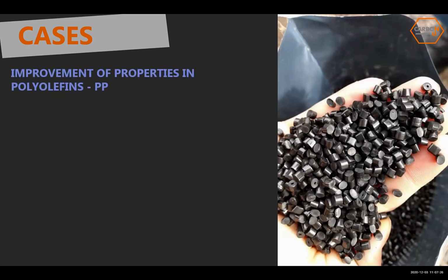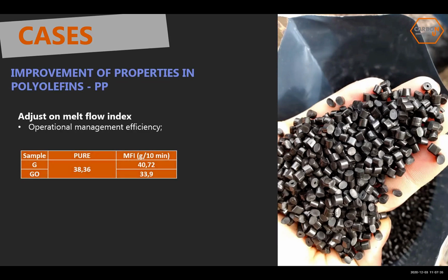So our case is the improvement that we started to do in properties, basically in polyolefins. So with polypropylene, we can adjust the melt flow index using graphene and graphene oxide. And this is a very good result because we can also work with operational management efficiency. I mean, once you work with a low melt flow index, you can achieve it for one grade. And once we have the same properties but a different melt flow index for injection molding, you can use two. So this is something that we are looking at.